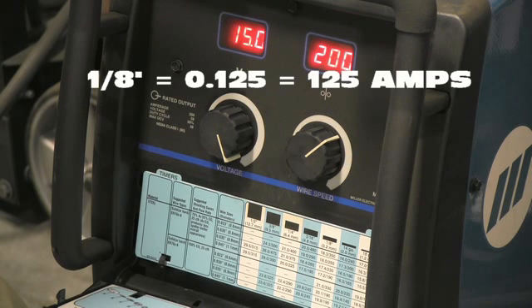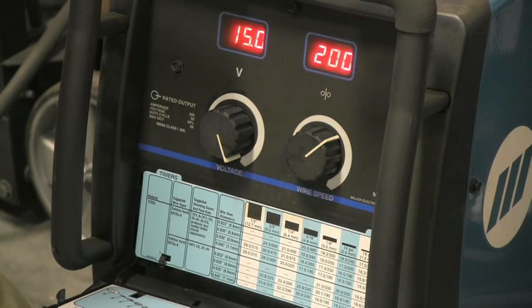So if an 1/8 inch piece of material in decimal form is 0.125, that tells us that we need 125 amps as a good starting point for that weld joint. Okay, well, that's nice and dandy and everything, but 125 amps, I don't see a setting for amperage on this machine. Well, you're right, you don't.